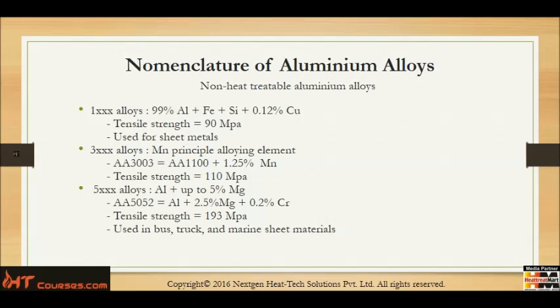Now we move to the 5XXX series, which is again pure aluminum plus up to 5% magnesium. Identified also as AA5052, which is pure aluminum plus 2.5% magnesium, 0.2% chromium, and you will notice the tensile strength now increases quite significantly to 193 megapascals. You'll find it used principally in bus, truck and marine sheet metals.